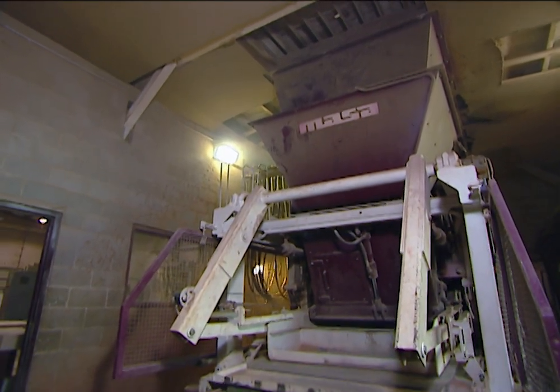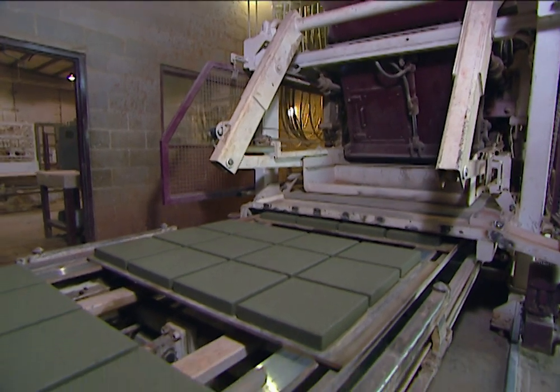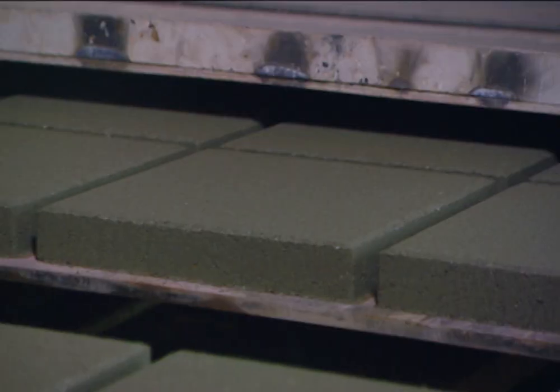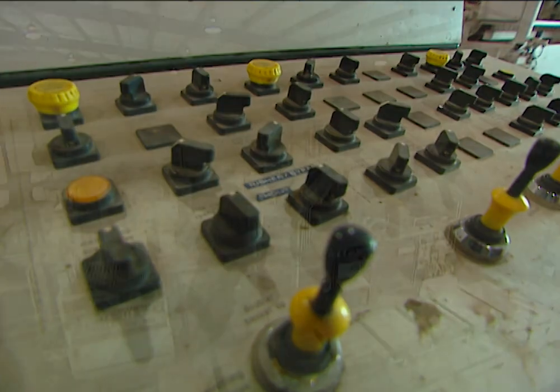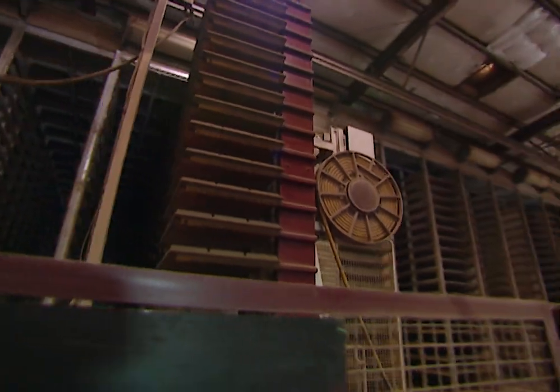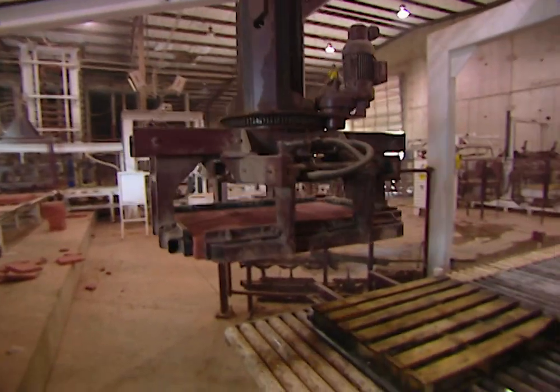When Tom says very high pressure, he's not joking. This machine is called the press, and it applies 2,000 pounds per square inch to the molds. The result is a product that's more than twice as strong as poured concrete. This machine can crank out a fresh layer of pavers every 13 seconds. The entire system is automated — computers control the raw materials mix, while machines stack and store the freshly molded pavers. They're allowed to dry for 24 hours in giant curing racks that stand nearly three stories tall. After sufficient curing, the pavers are ready to be shipped to the consumer.